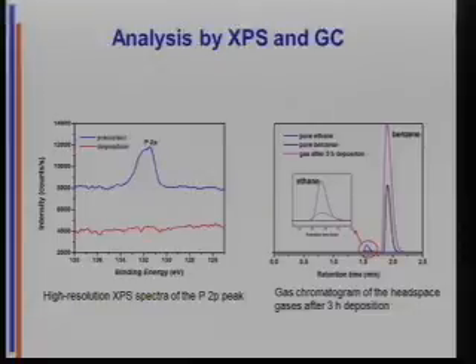Phosphine? Nope. So this is the XPS phosphorus region of what the precursor looks like. That's the gold nanoparticles. The phosphine all ended up in the benzene solution. Okay? What happened to the methyl groups? Eventually reductive elimination to form ethane off the gold nanoparticles. And so we can make size-controlled gold nanoparticles with absolutely clean surfaces. And by the way, they're great at SERS. That's in the paper if you care. But it's a cool way of doing synthesis.